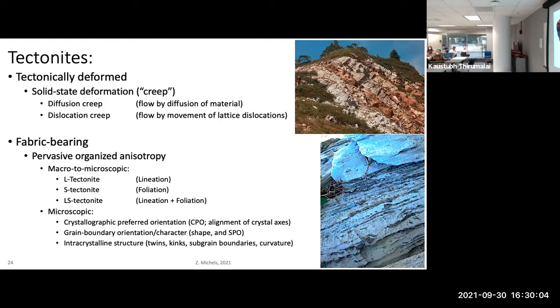The rocks that I focus on have been deformed in the solid state. So they creep, meaning the deformation is not fast, they're not molten at any point or at the point that they're flowing. And there's two ways that can happen, either by diffusive mass transfer, where material is diffusing from regions of high stress to low stress, or by what's called dislocation creep, where inside the crystal lattice, you actually have discrete movements of the lattice plane across unit cells under stress.